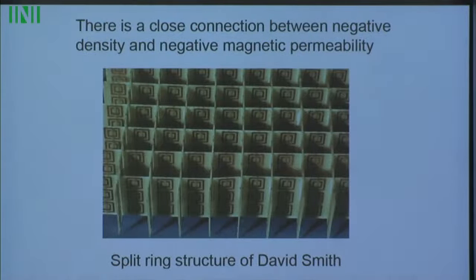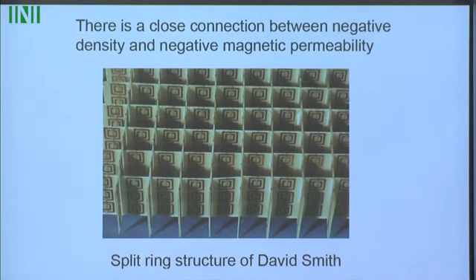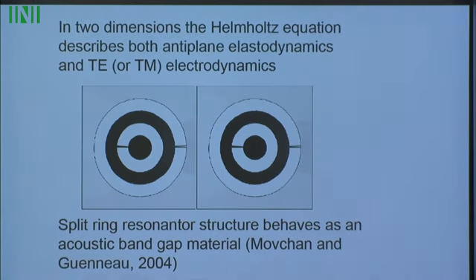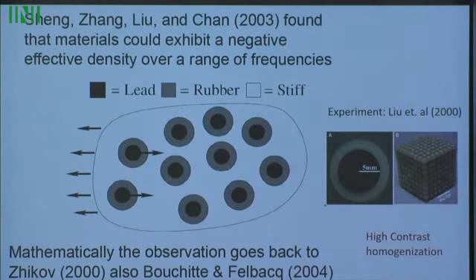And in fact, there's a close connection between negative effective density and negative magnetic permeability. This is a split ring structure of David Smith, giving a negative magnetic permeability. And as observed by Movchan and Guenneau, of course, the Helmholtz equation describes both antiplane elastodynamics and TE or TM electrodynamics. And so you can use the same structure to basically give you a negative density for antiplane vibrations. If you vibrate this back and forth, you will get a negative density.